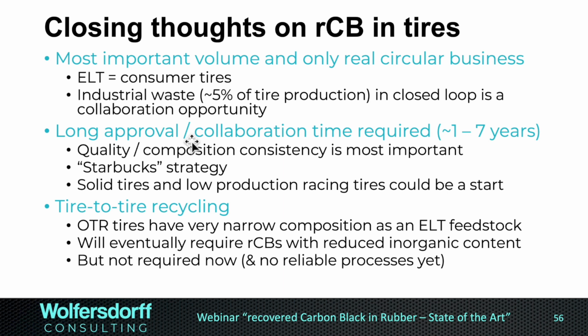What is interesting in the closed loop, in collaboration with a tire maker, is that we can know what is in there, so that we can really select the feedstocks for the pyrolysis operation. Tire has a very long approval and collaboration time, because no tire maker will approve a recovered carbon black without knowing the company. And the approval time really is between 1 to 7 years.